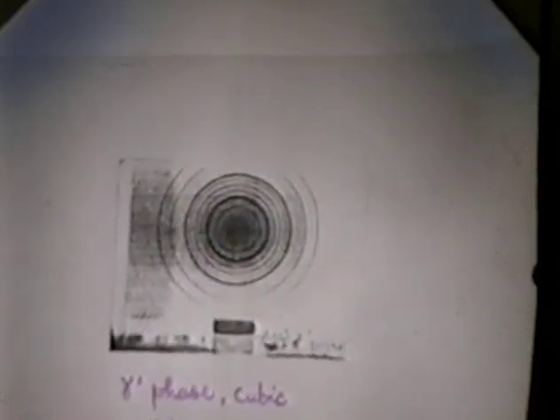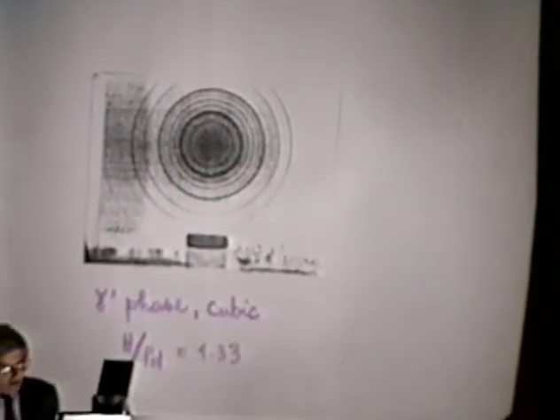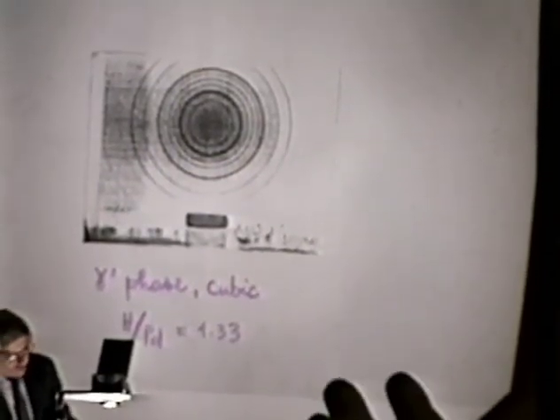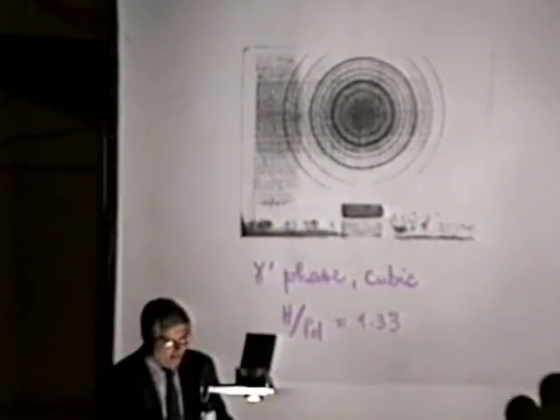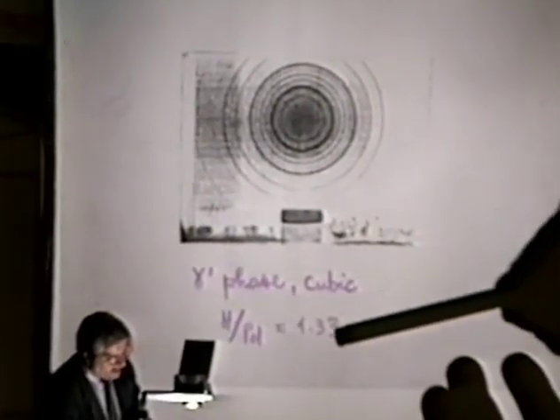How do we know that this is cubic? Because the diffraction pattern is very clean now, and the ratio between the rings is what is expected for a cubic structure by Fourier analysis. And there are no vacancies, and this phase is stable after many years. It was the same phase which was found in 1988, and it is stable for a long time.